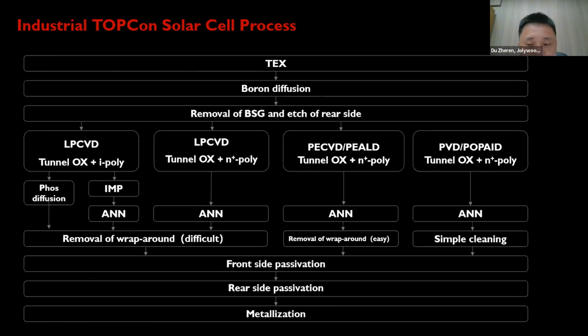So for LPCVD technology, with or without in-situ doping, this wraparound removal process is essential. And the removal process is very difficult because it's very difficult to control. And it may cause some yield issues with other visual defects, and also some negative impacts on the cell efficiency.